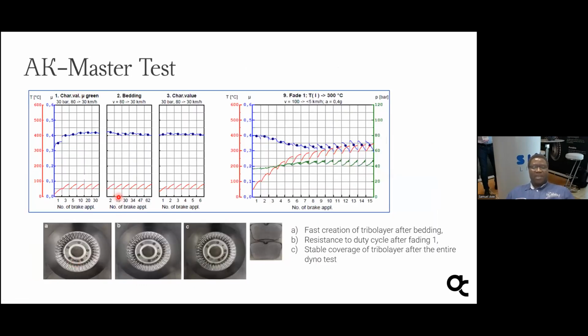Here is the result from AK Master. Here I show the first three test procedures and the fade test. What we can see at first is a quick creation, the building of a coefficient of friction. We see it increase quickly at the beginning. The coefficient of friction is almost around 0.4 or 0.3. And in the bedding section, we see that this is also maintained and sustained even after bedding, which shows the stability of the coefficient of friction.